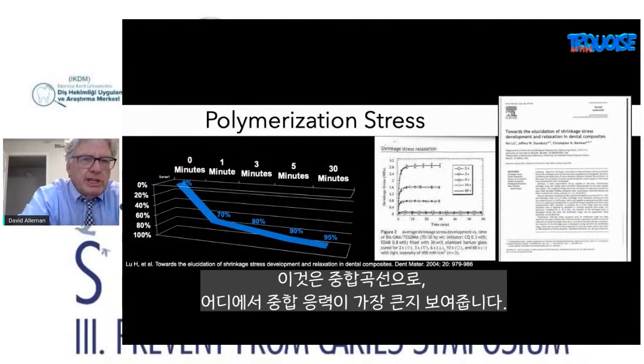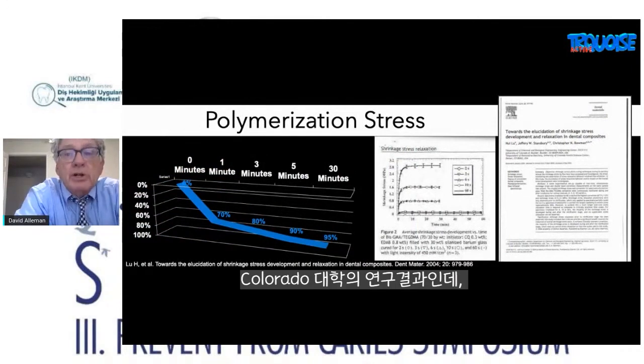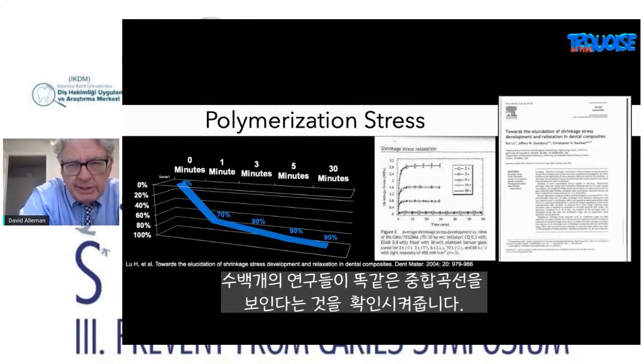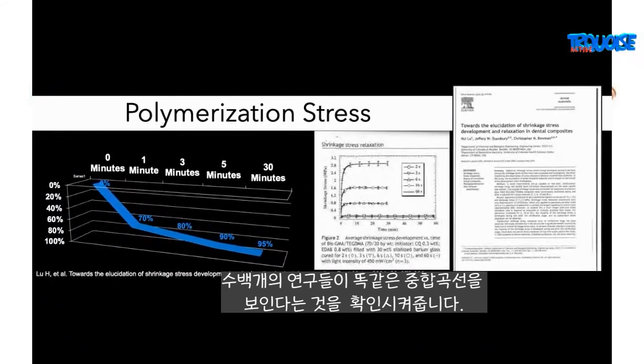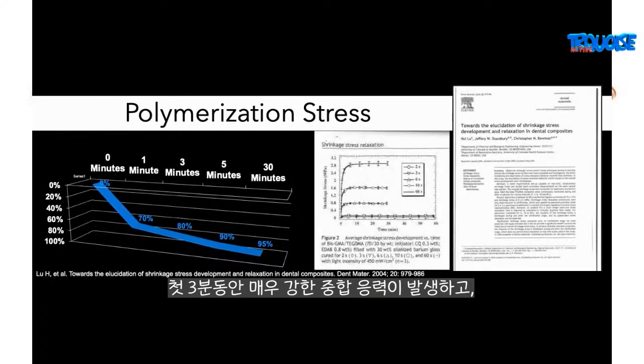So this is a polymerization curve, and this indicates where polymerization stresses are the greatest. And these curves, this is a study out of the University of Colorado, but it confirms hundreds of studies showing the same polymerization curve: in the first 3 minutes, you have a strong polymerization, but after 3 minutes, the polymerization tapers off. And after 30 minutes, it's very minimal.